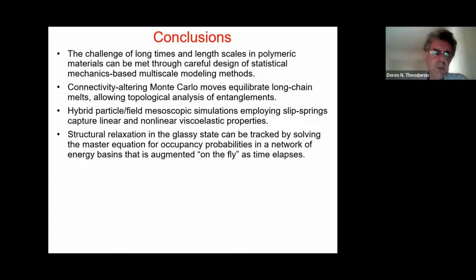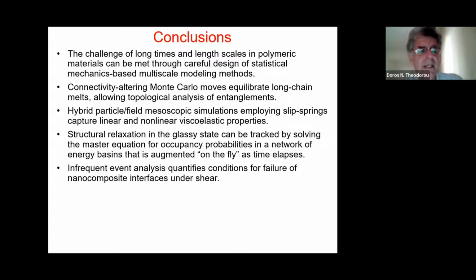seems to be useful. We can calculate rate constants, and then we can incorporate this picture into a picture of a network of minima that is progressively augmented as time goes by, and see how the probability of occupancy of these minima evolves with time. And remarkably, the way in which this probability of occupancy evolves seems to indicate specific segmental relaxation events, which are also observed experimentally in a glass.